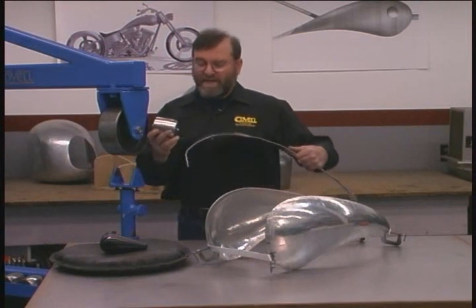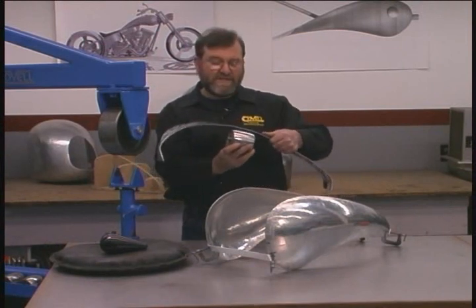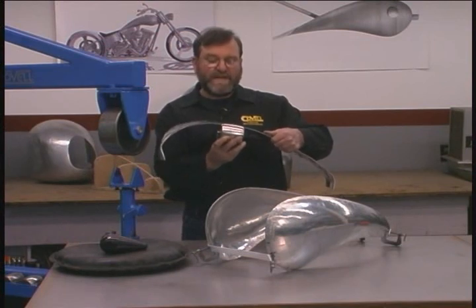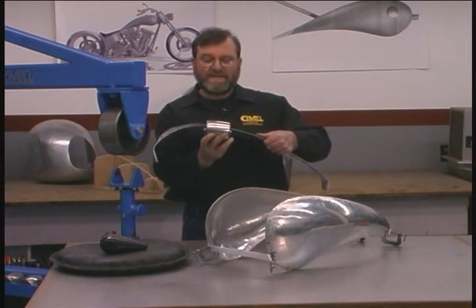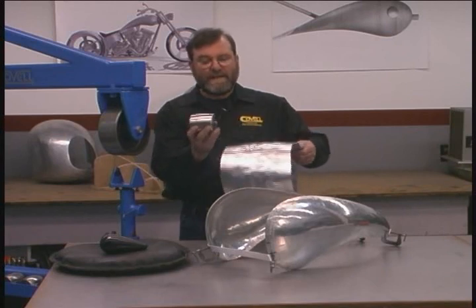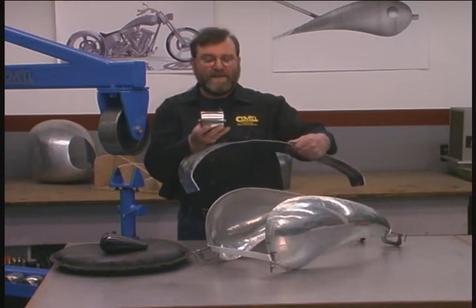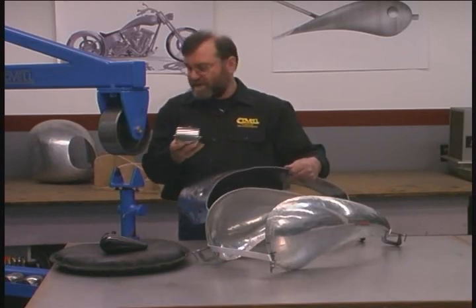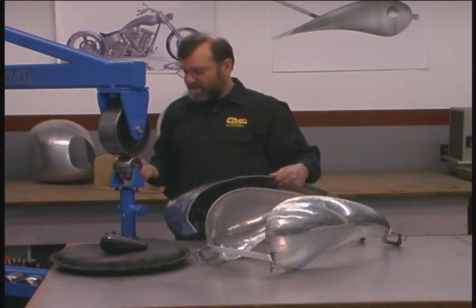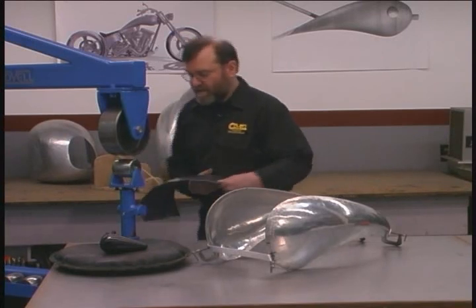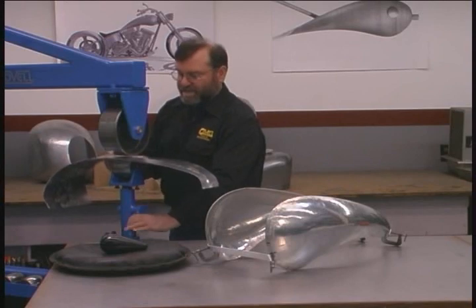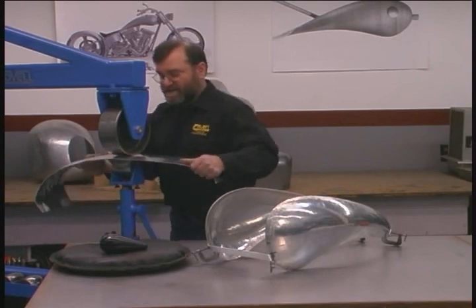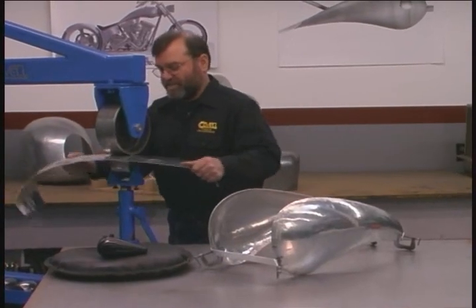I'm choosing a wheel that has a contour that matches the shape of this part from front to back. You might notice that this is a flatter contour than will fit side to side. We can only wheel right to left on this part, but the result will be a smoother part. So we'll put the wheel in the machine, put the part between the wheels, and start the smoothing operation.